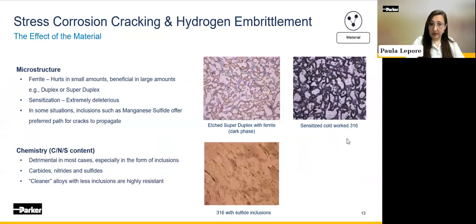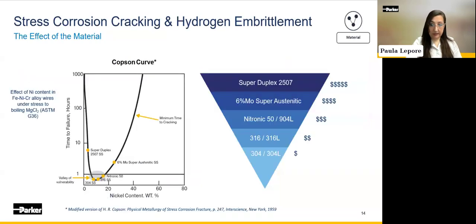Talking about the third and last pillar here, materials can be more or less susceptible based on their microstructure and chemistry. Issues like sensitization, that you see here on the second picture on the left, big inclusions, you see the picture down below of 316 with big sulfide inclusions, or large amounts of ferrite, carbides, and nitrides or sulfides, like the first picture there, where you see a super duplex with dark phase. These can be highly deleterious, and they will definitely accelerate the process of stress corrosion cracking and hydrogen embrittlement.